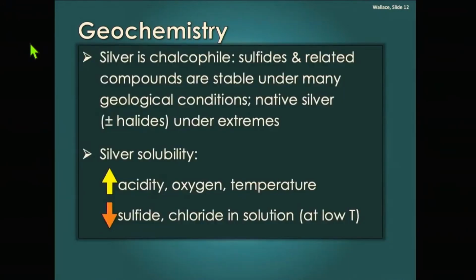So if I would take anything away from that, silver solubility: if we change the acidity, if we give it acid, if we give it temperature, it becomes more soluble and we can move it around. But as soon as we introduce it to sulfide, or we put chlorine in solution, just like we had in gold, in this case, it's going to change the way it's going to interact. So this is again just the framework to set up where we're going with the minerals, because you won't believe some of the things I'm going to tell you later on unless you believe this.